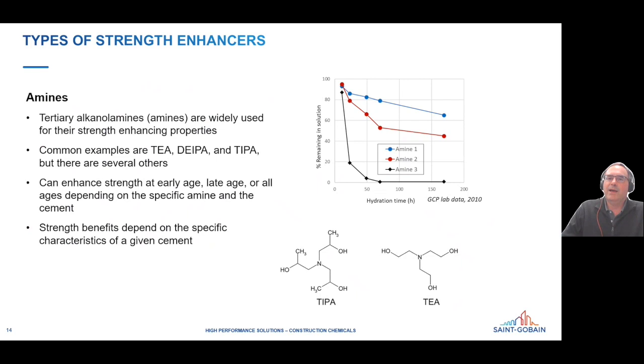And so this plot here is just showing how these amines actually remain in the pore solution for long periods of time. So this is going out to a week here, and you can see even after a week, half of the amines that were added are still there to do their work. And so that's how they're able to increase the strength at late ages.